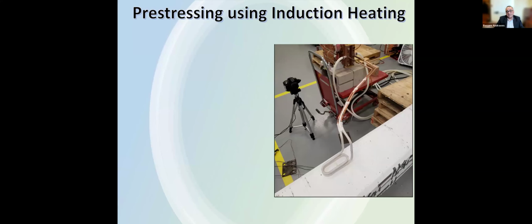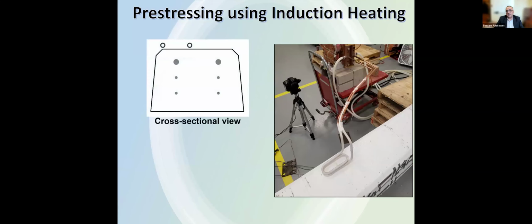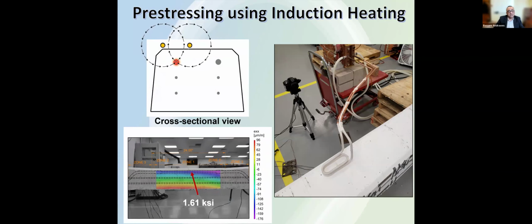And what we did was basically we heated the SMA inside of these ties with this coil. And we were able, not only that, but just by scanning the top surface of the concrete without even touching the SMA inside, to reach pre-stress at the top fiber as high as 1.61 KSI. Which resulted in a moment cracking capacity that exceeds even the AREMA requirement. So that was a very exciting thing to see here.